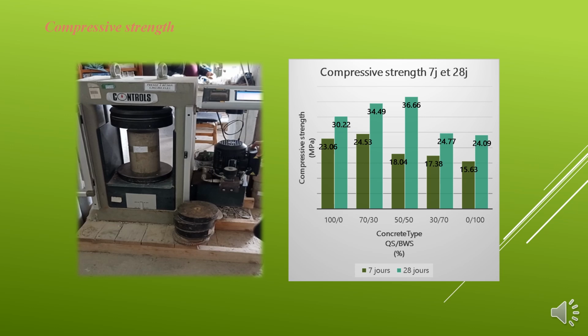Finally, we will discuss the last test, the compressive strength, as shown in this figure. According to the curve and this analysis at 7 and 28 days, it can be concluded that the compressive strength decreases markedly as soon as the rate of replacement of natural aggregates by recycled aggregates exceeds 50%, and that this reduction can exceed 10% of the resistance of the control concrete, so 100% natural aggregates.